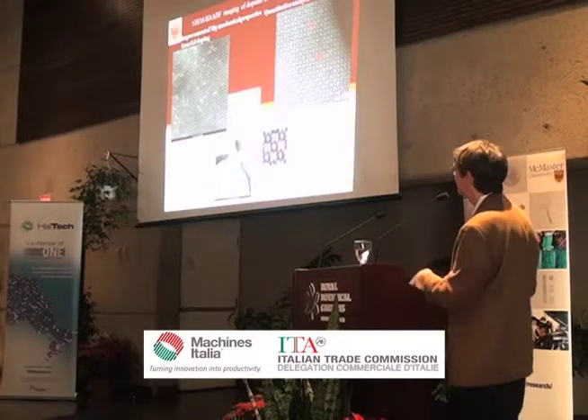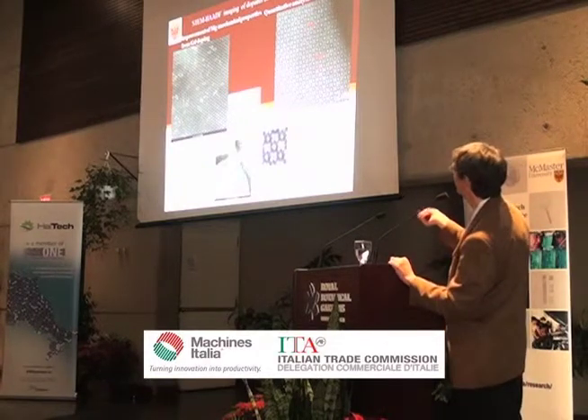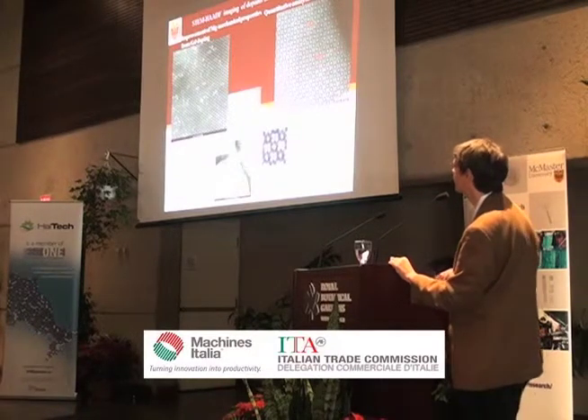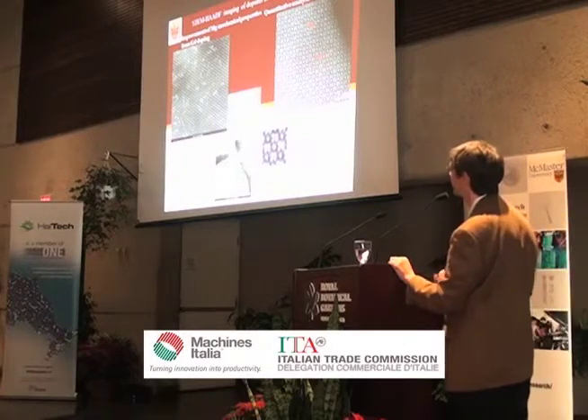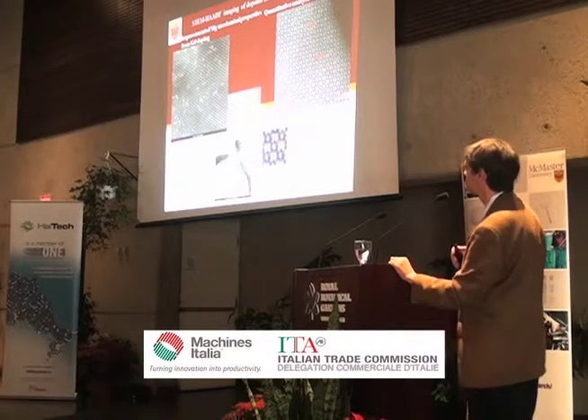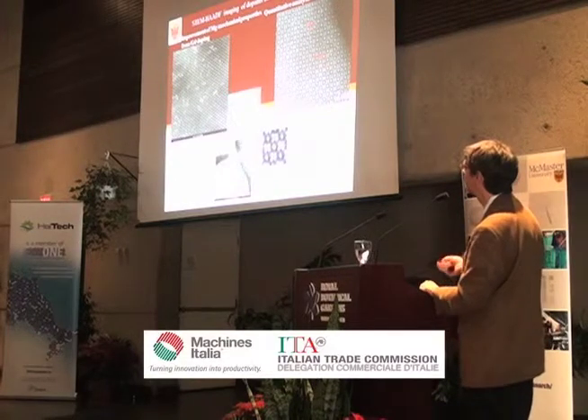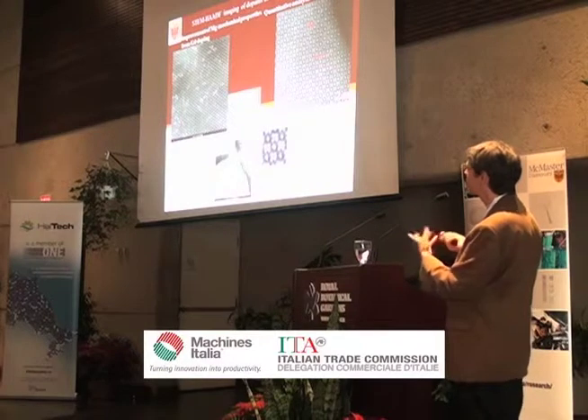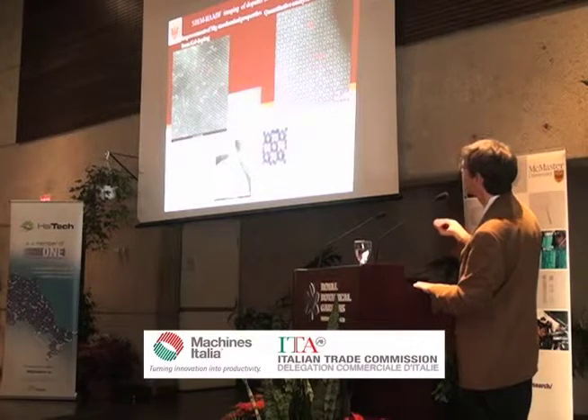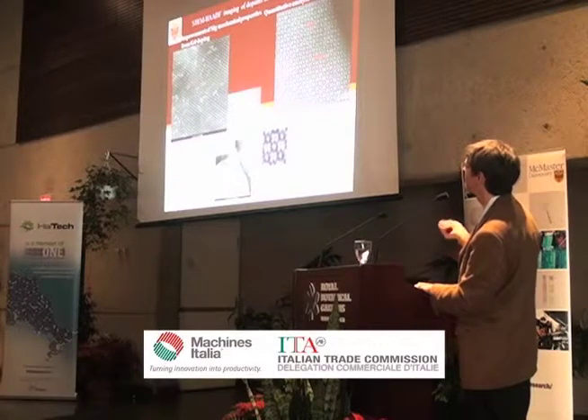Okay? And we can see even, not just in esoteric materials such as superconductors, but in structural materials. This is magnesium. It's a lightweight material used in cars. General Motors is using magnesium in cars at the moment. They're working with us to understand corrosion. And in this application here, to try to make magnesium stronger, because it's a very soft metal, but by adding an appropriate amount of elements such as gadolinium, which is a bit expensive, but you don't put a lot, in this case use less than 1%, then you can strengthen it, and these are actually individual atoms of gadolinium present in the matrix of magnesium.